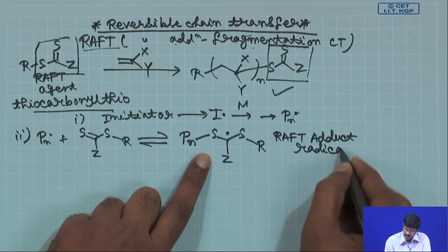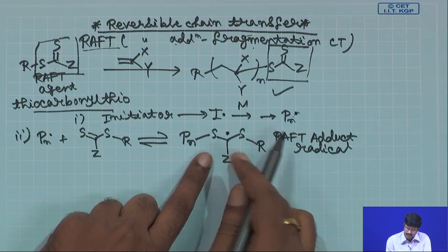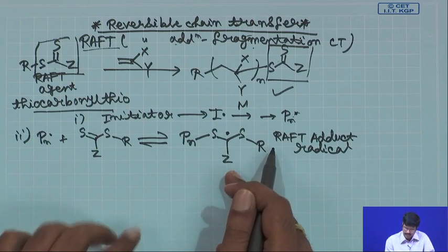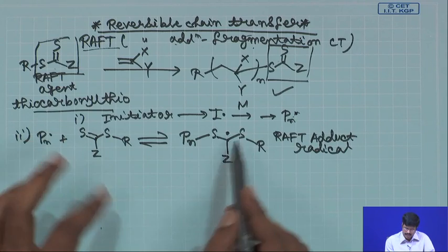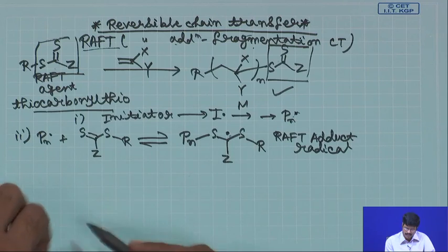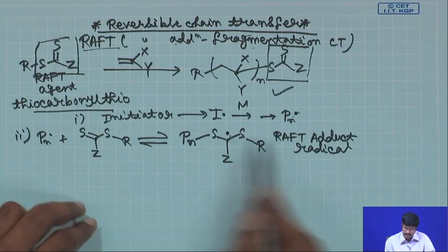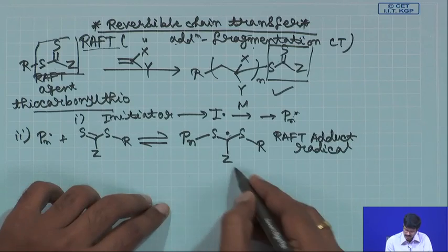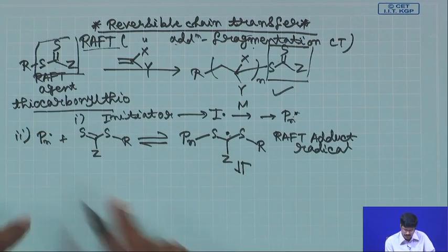This is your persistent species that we are talking about here in this case. This is not reactive enough to react with the monomer itself and start propagation of the chains. So, basically it does not react with the monomer and transfer the radical and then start propagation. It will basically react with this polymer and create a persistent radical like this afterwards. So, it can go in this way or that way, both ways.